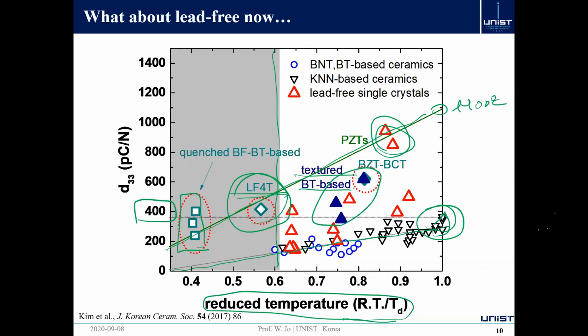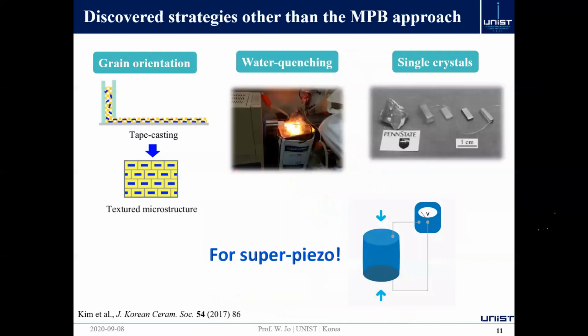So that means all three techniques, single crystal, LF4T which is also a textured material, and water quenching, they all seem to give unexpectedly nice results, better than you expected. So this literature survey summarizes into three techniques of potential interest. As I already told you, grain orientation, we say TGG, templated grain growth, water quenching, and single crystal. These three should be highly utilized by people working on lead-free piezoceramics afterwards.